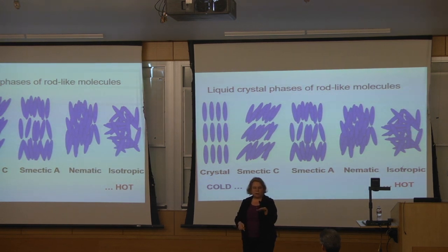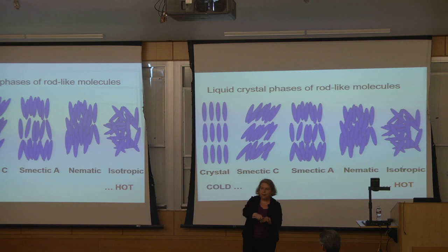The liquid crystal is north-south on one surface because the material has been rubbed so that the liquid crystal lies, with their rod-shaped molecules, they lie parallel to the north-south direction. And on the other face, east-west, in between they twist. You put a little bit of chiral dopant in the liquid crystal to make it always twist in one direction, okay? And then you put cross polarizers. And because of the twist, light can actually get through the cross polarizers because the light rotates through the twist,